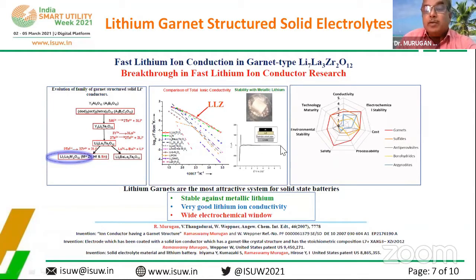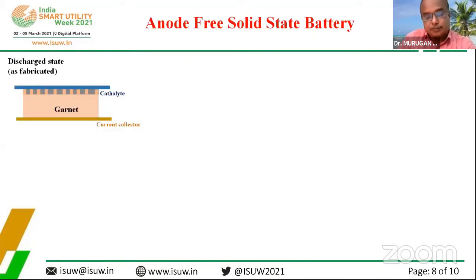And you can think about a battery with a potential which is quite large, up to above 7 volts. If you look at the figure of merit compared to the sulfides, perovskites, and borohydrides, or whatever it might be, it's much, much higher compared to any other component of these kinds. That's the reason why it's the most attractive system for solid-state batteries. The characteristics which make it most attractive are stability against metallic lithium, very good lithium-ion conductivity, and wide electrochemical window. This material was invented in 2007. It's really the biggest breakthrough and really changed the world as far as the solid electrolyte is concerned.